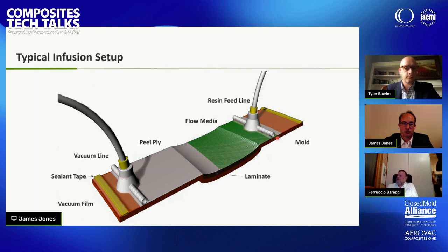So resin feed lines like this spiral tubing are strategically placed to distribute resin along the length of the blade, and then it can flow across the laminate towards the vacuum. The vacuum line is placed around the perimeter to maintain full vacuum on the part throughout the infusion. And there are specialized connectors that connect the resin feed lines and the vacuums to our vacuum pump and to our resin source. And all these process materials are sealed onto the mold with a vacuum film that's sealed with a specialized sealant tape.